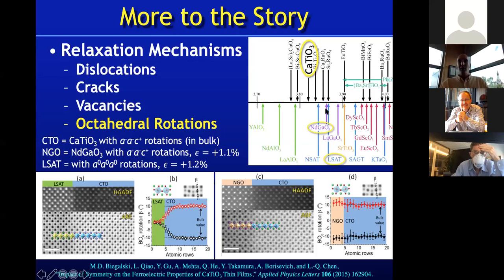But from a pseudo-cubic perspective, if we look at the volume of the unit cell and what that pseudo-cubic lattice parameter would be by treating it as a cube, they have almost identical pseudo-cubic lattice constants. One's 3.86 and one's 3.87 angstroms, so they differ by a hundredth of an angstrom.